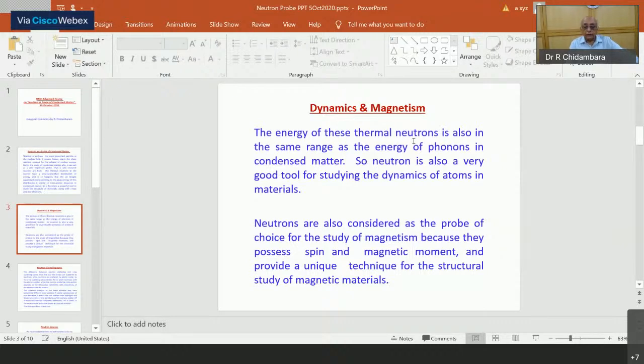It also so happens that the energy of these thermal neutrons is in the same range as the energy of phonons in condensed matter. So neutron is also a very good tool for studying the dynamics of atoms in materials. Neutrons are also considered as the probe of choice for the study of magnetism because they possess spin and magnetic moment and provide a unique technique for the structural study of magnetic materials. The groups in BARC have done pioneering work in all these fields related to neutron scattering. First at the Apsara reactor, and then at the Dhruva reactor. And these groups still remain strong and very productive.